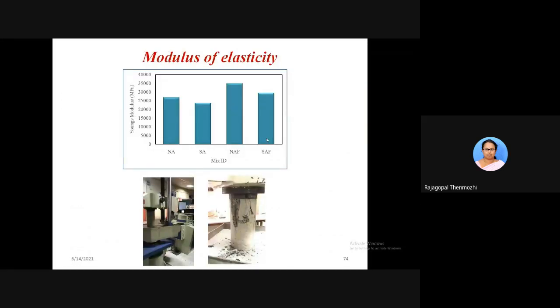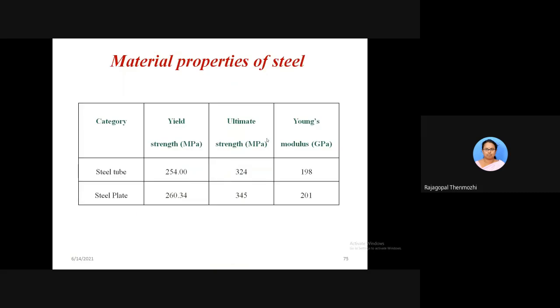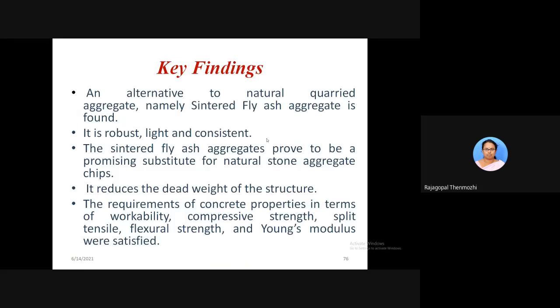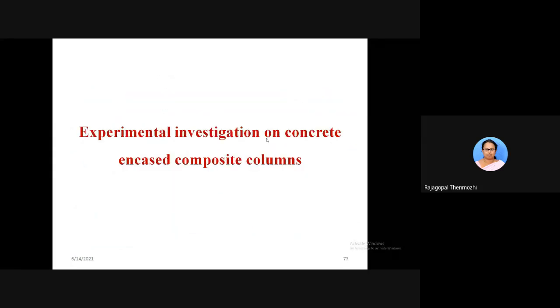And these are the modulus of elasticity values, and the steel tube is tested for yield. From this, based on the mechanical properties, the sintered fly ash aggregate can be effectively utilized for making concrete because it gives good workability. The compressive strength, split tensile strength, flexural strength and Young's modulus are satisfied.